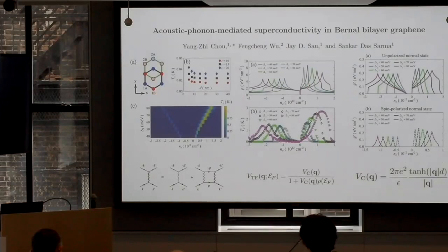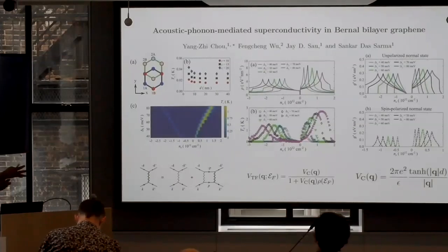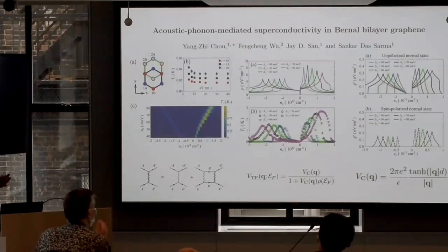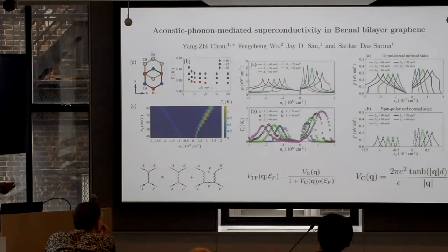Look at the TC we are getting here. TC we are getting is of the order of 1 Kelvin. And look at the experiment. TC is 40 millikelvin, right? So this is a huge difference. Maybe if one does a Hubbard model type calculation that Andy was alluding to, that I certainly was not familiar with, maybe the 2 systems will have very different TC directly. But within our model, the only thing I could think of is that the mu star effect is very strong.